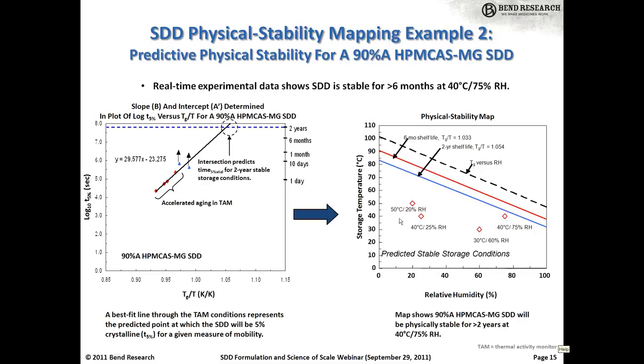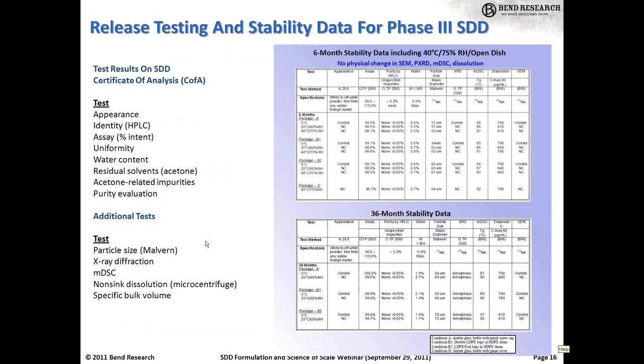So that's the kind of exercise you can go through to be more rigorous beyond the sort of rule of thumb exercise. And finally, just to show, all that prediction is nice, but of course this is done in parallel with gathering real-time stability data. The idea is you're pulling those samples and checking that you're matching your prediction, rather than hoping for the best. And there is plenty of real-time, real-world stability data like what's shown here.